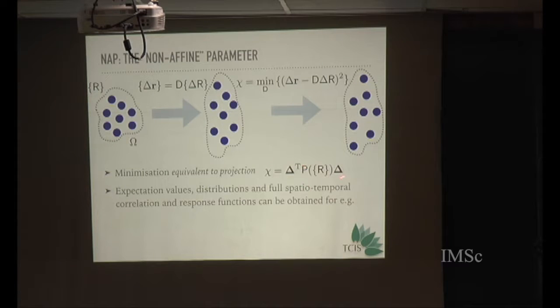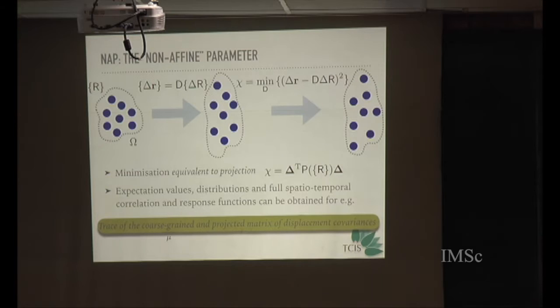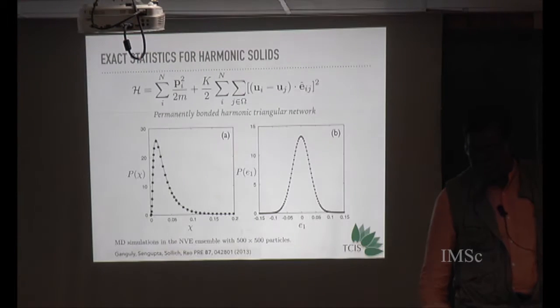Okay. So once I have a microscopic definition of this non-affine parameter, one can calculate expectation values, distributions, full spatio-temporal correlations, response functions, everything, like any other standard thermodynamic variable. For example, the thermal average of the non-affine parameter turns out to be just a trace of PCP, where C is just the displacement correlator. So if you calculate the displacement correlator and project it, then the trace of that, the sum of the eigenvalues, gives you the non-affine parameter. So the English definition is, it is the trace of the coarse-grained and projected matrix of displacement covariances. Very simple. Okay, and you can do it locally, and you can calculate global values, whatever.